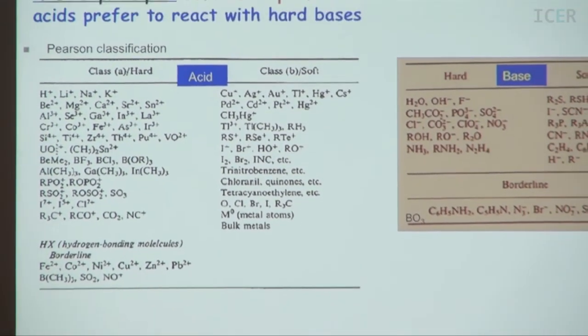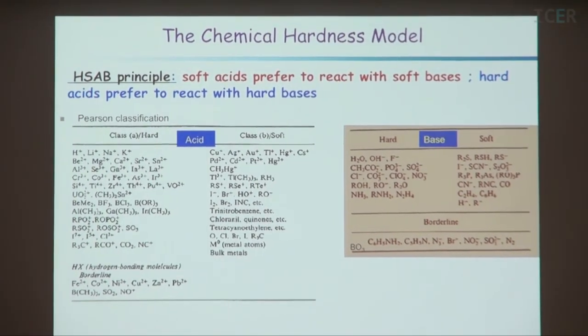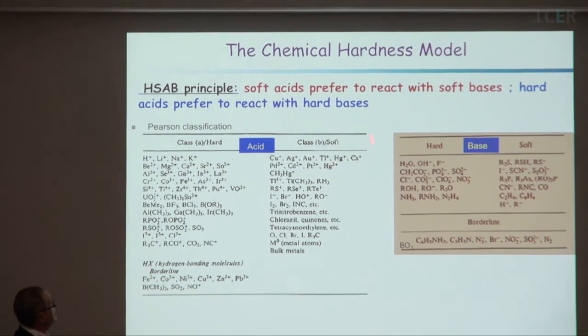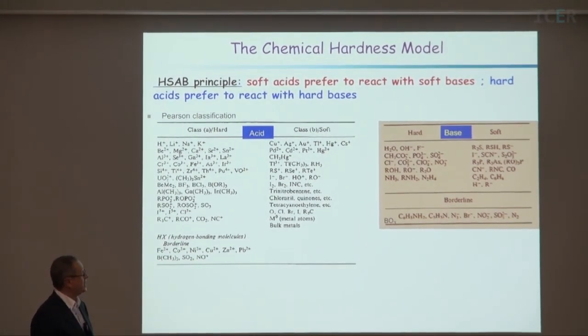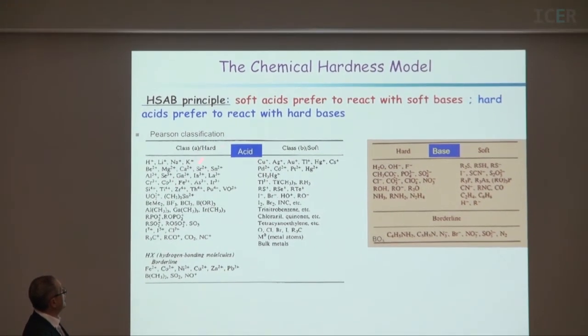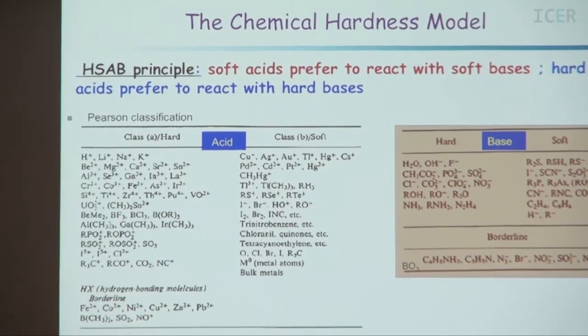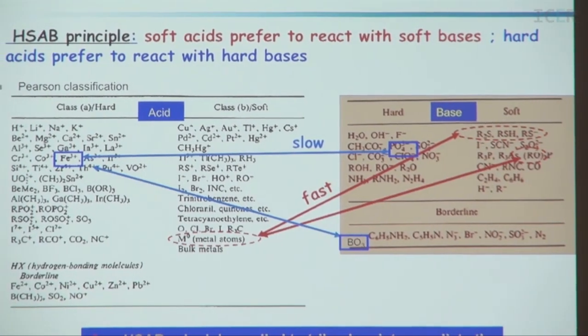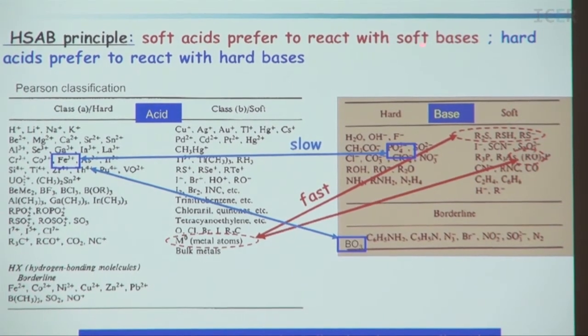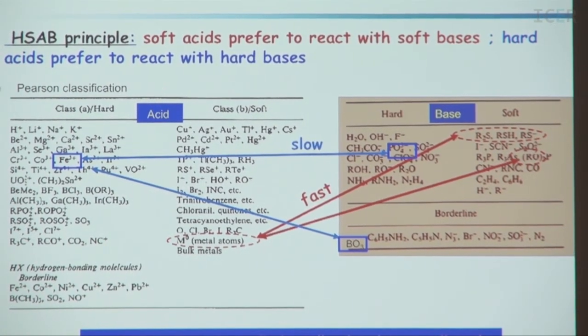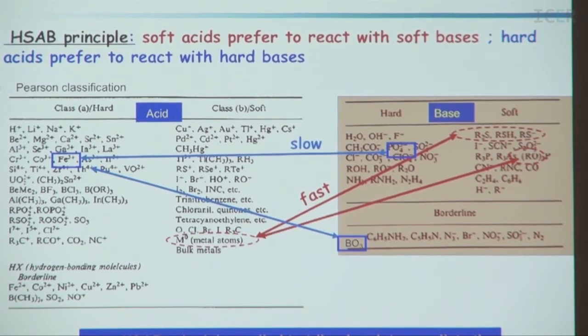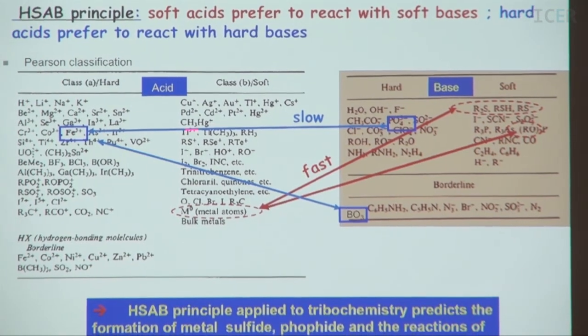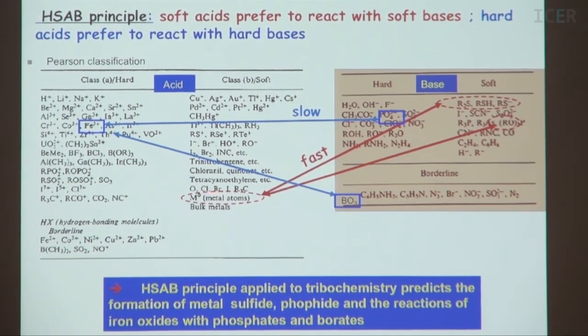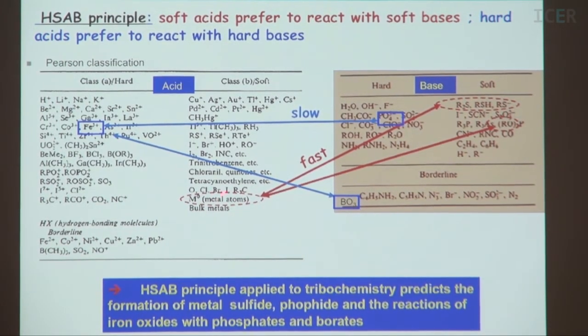Okay, all these reactions that I showed you before, sulfide, phosphide, borates, can be explained very easily by the HSAB principle. This is a classification of acids and bases. According to this principle, soft acids prefer to react with soft bases, and hard acids prefer to react with hard bases. This is well known in chemistry, and you can see here that it works because, for example, metal atoms like iron prefer to react with soft species, with sulfide and with phosphide.